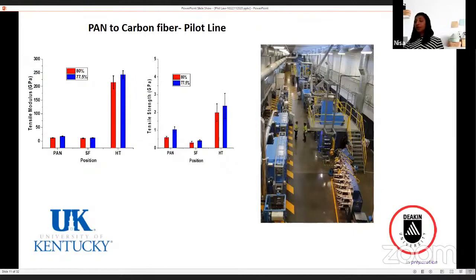So here is the picture of the carbon fiber production line at Deakin University. We have carried out the stabilization and carbonization process in this production line. So here is the work where we carbonized the fibers we spun at University of Kentucky. You can see that by making a slight change in the spinning condition, that is the coagulation conditions, that can affect the final carbon fiber properties.